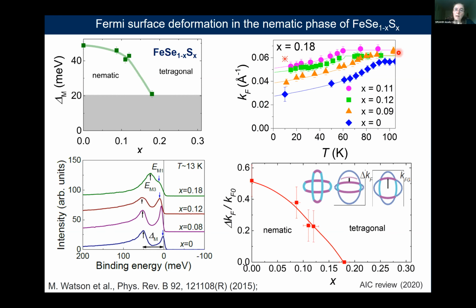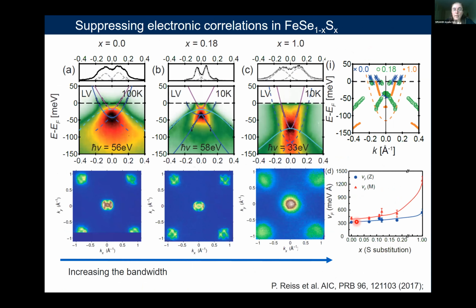These are cuts for the Kf value for the electron pockets, and here we look at the relative elongation of these pockets in relation to their tetragonal case. And we can see that this elongation of the Fermi surface is suppressed at about 18%, which is where nematicity disappears. So this is direct evidence of the existence of the nematic phase and how it changes.